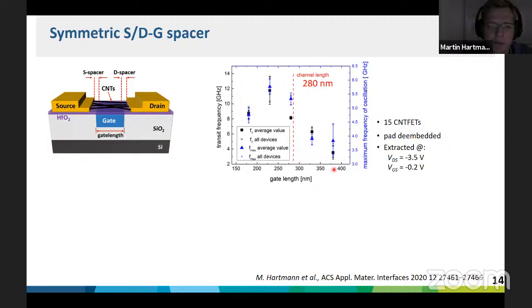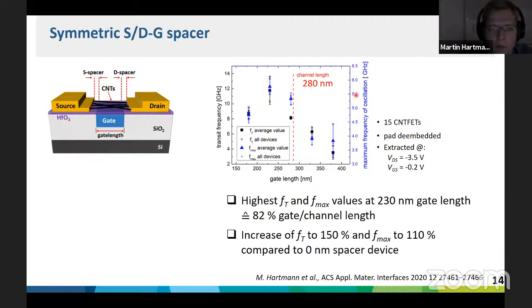All the gate lengths above the channel length mean that there is an overlap, or an underlap, between the gate and the drain and the gate and the source electrode. Smaller values mean, of course, that there is a positive source spacer. And what did we see? Our fastest devices operated up to 14 gigahertz transit frequency, corresponding to a maximum frequency of oscillation of about 5.5 to 6 gigahertz. This is not too high, but considering our long channel length, this is quite reasonable.